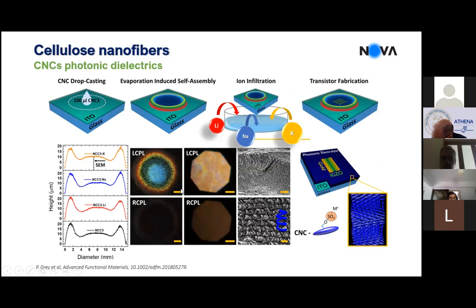This could be explored, and I will explain later how, but you can also modify these membranes chemically. You see the cross section here, with the crystals with this rotation. The structure is not perfect, and so the pitch is not perfect. And you see here why you can have different colors in different regions of these membranes. But there are ways to control it, and we have been working on that, not only to control the color, but also the drying process, in order to have a uniform color all over the membrane.